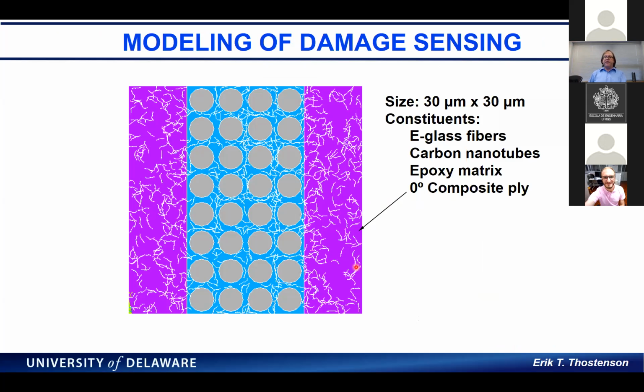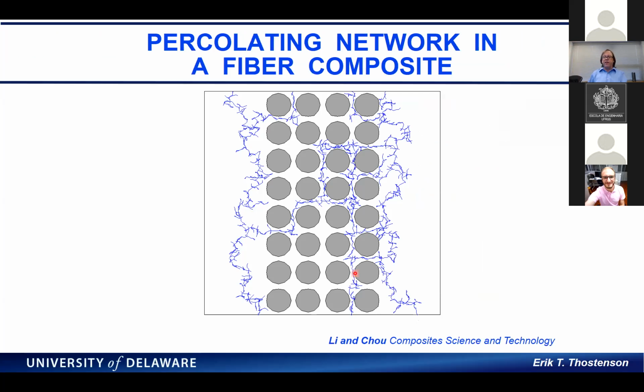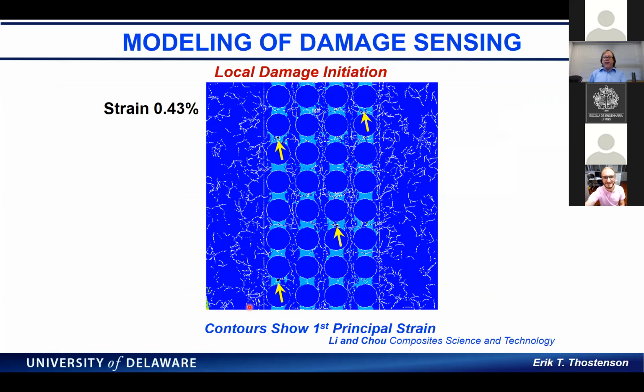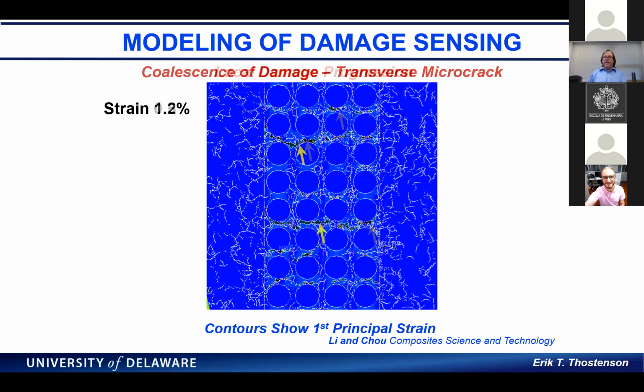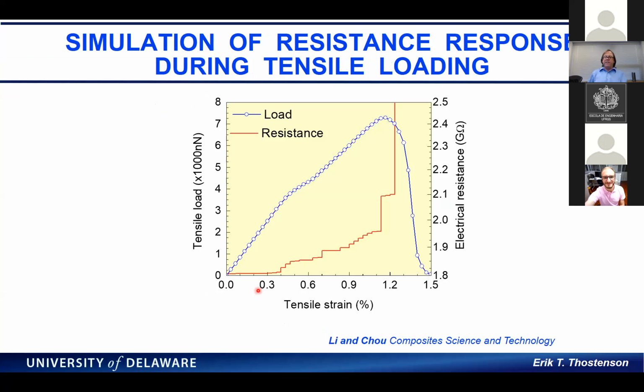A colleague of mine has also done some modeling work in this area. We're looking at the creating of a nanotube network in situ, creating of a finite element mesh, and then looking at that damage initiation and the eventual coalescence into a transverse crack. And the results quantitatively are not the same, but qualitatively match very well. In particular, the linear elastic part, up until you start getting cross-ply cracks and then those jumps.